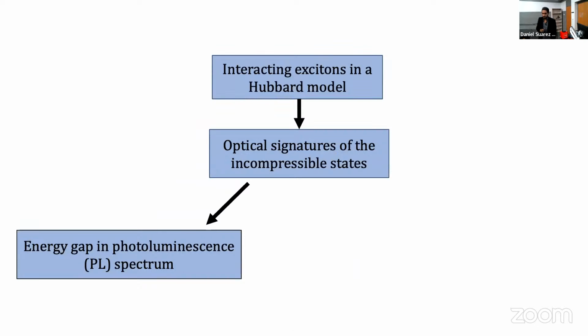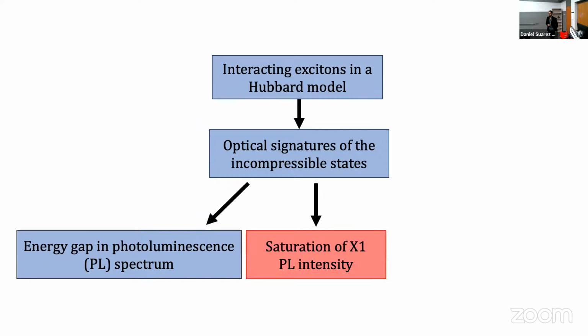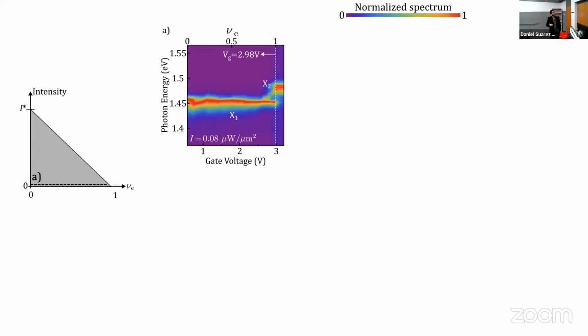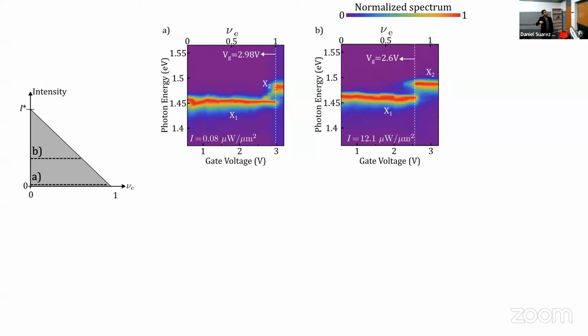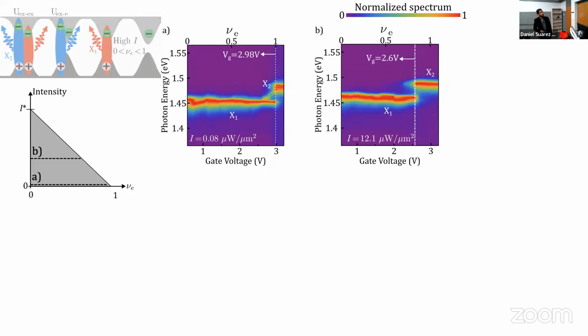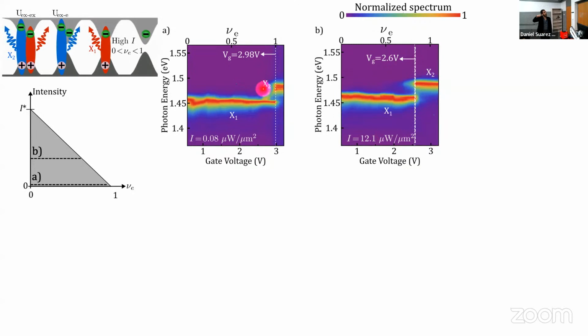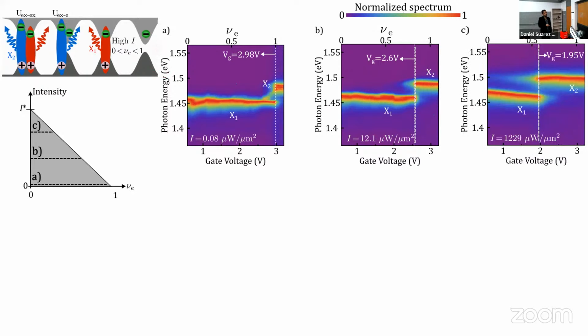And so that was the first observation, the existence of the gap. The second observation is the saturation of the PL intensity. So far, I have mentioned how the existence of the gap benchmarks the formation of incompressible states. For different pumping intensities, we have different voltages at which these states take place. And we can then reach a situation in which we have a Fermi-Bose mixture in the material.